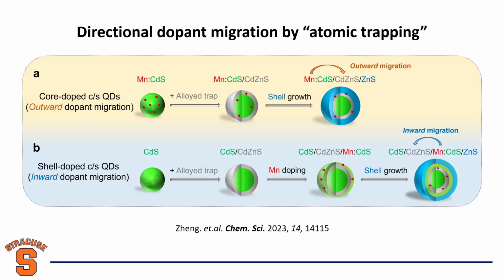For example, we want to have an outward migration. We intentionally grow the trap layer. We start with the doped core and the trap layer, and then the dopant migrates outward to the trap layer. If you want an inward migration, we start with an undoped core and the trap layer, then the dopant in the outside shell can move back to the trap layer. So we can specifically control the dopant depth, the exact location in core multi-shell crystals.